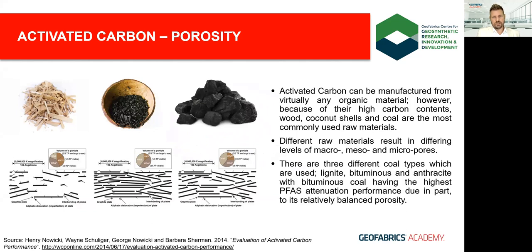Commercially, activated carbon is produced at scale from wood, coconut, and coal, and can also use waste materials such as apricot kernels and cherry pits. Different feedstock materials and processing techniques result in different properties including specific surface area and porosity. Porosity is categorized by pore size: micropores less than about 2 nanometers, mesopores from 2 to 50 nanometers, and macropores above 50 nanometers. Wood-based activated carbon generally has more macropores; coconut shell has higher micropores; coal is somewhere in between with balanced porosity. Research has shown higher PFAS attenuation capacity using bituminous coal over the younger lignite or older anthracite types.